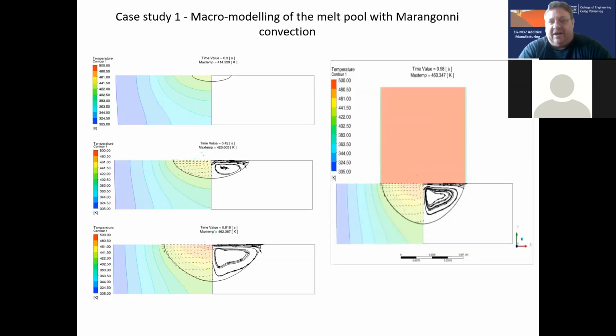Downwards, correct. Absolutely. So if the melt pool had gone in the other direction, say if we'd had this convection cell coming up back into the laser, then it would have transported heat down the center line towards the bottom of the melt pool, and it would have become elongated. So the melt pool would have become, anybody? No, it's not just keyholing. It looks like keyholing, but it's not. But I'll come to that now. So the melt pool would have become deeper. You would have had an elongated melt pool. It isn't keyholing.